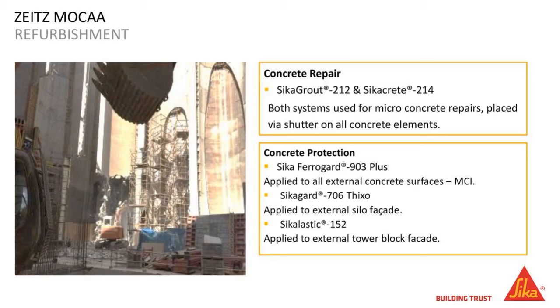For the protection of the silos, based on the client wanting to see the concrete, we couldn't use any type of coating system that was visible. So we had to go for a silane system on all the concrete elements. With the testing done, the chloride concentration was below 2%, which meant that we could also apply a product called Sika Ferrogard 903 Plus, which is our migratory corrosion inhibitor system, mainly put on to try and repassivate and give the structure a boost of life with regards to the rebar passivation.